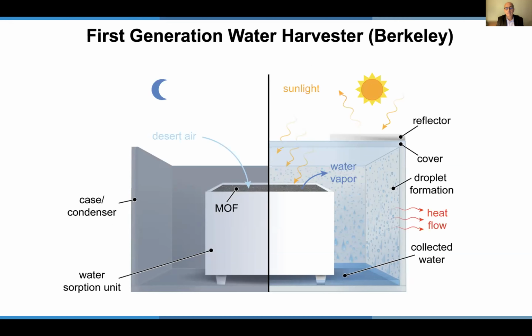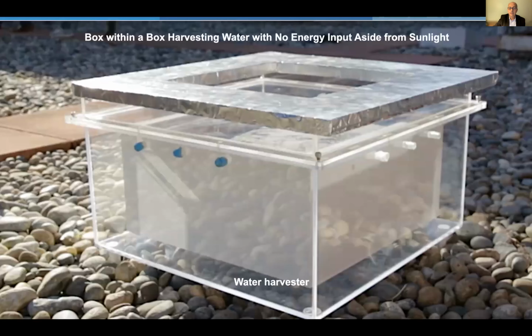in the desert. So my students designed a prototype, which is very simple, a box that is installed within a larger box. In this internal box, you have, in this particular experiment, 1 kilogram of MOF, and it was exposed to desert air. This was in the Arizona desert. Water from air goes into the MOF, and then during the day, you close the larger box and expose it to sunlight, thereby heating the interior, and water comes out of the MOF and condenses on the walls of the larger box. And in so doing, you harvest water.